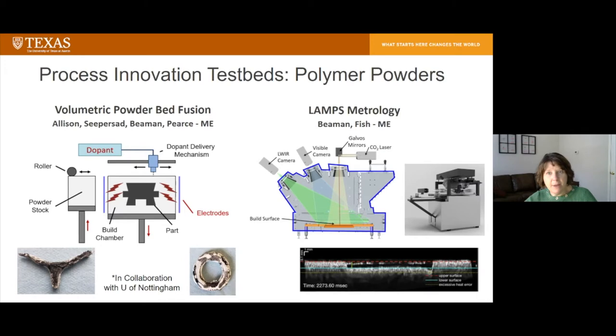A couple of polymer powder bed fusion innovative processes that we have under development. On the left-hand side is something developed by Jared Allison as part of his PhD dissertation aimed at enhancing the speed of selective laser sintering. So in this case, what we do is we deposit dopants that are electrically conductive into a polymer powder bed, and we selectively deposit those dopants, and then we apply an electromagnetic field, in this case radio frequency, to the entire powder bed at once, and it heats only the areas that have been selectively doped. You can see a longhorn on the bottom left that Jared fabricated.